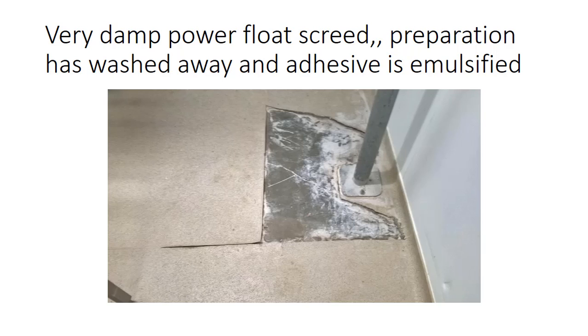This clearly shows the power float concrete and what's happened. The very damp power float screed, preparation has washed away, so even the screed has gone, and the adhesive has emulsified. This adhesive would have been yellow in colour originally, and it's gone to white, gone very, very thin, and started squeezing out through the joints, and eventually just went to powder.